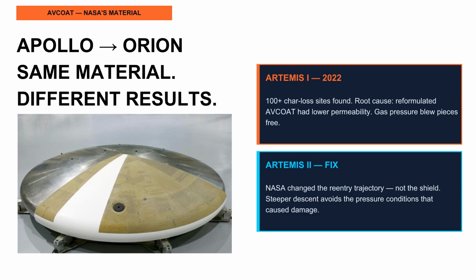NASA revived AVCOAT for the Orion capsule. The formulation was slightly updated, and that update had consequences. After Artemis I in 2022, post-flight inspection found chunks of char had broken off in over 100 locations. The root cause, the reformulated AVCOAT had lower permeability. Pyrolysis gases could not vent outward normally. Pressure built beneath the char layer and blew pieces free.